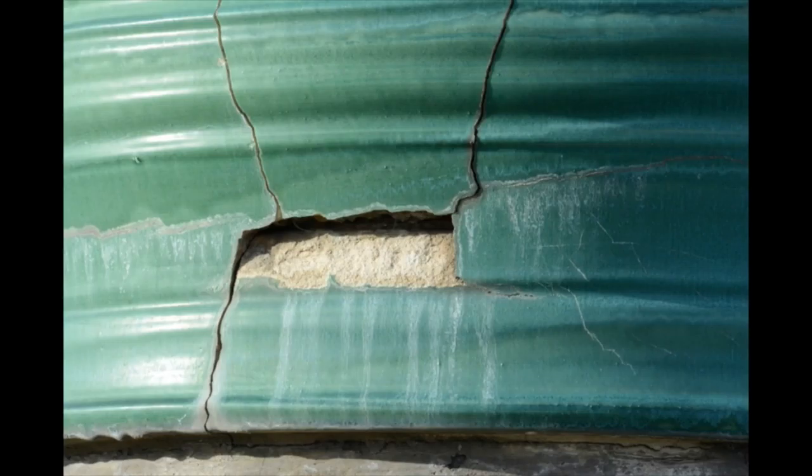The particular failure here — right in here, it's hard to see in the image — you're looking through up at rebar. The rebar is exposed. The rebar was too close to the surface of the concrete as I fed it on, and it split the piece apart. As the rebar has expanded via water, it is starting to take that piece apart. This is probably the worst problem on the piece currently, and the cracks that are extrapolating out from it result from the different expansions and contractions of those dissimilar materials in direct contact with each other.